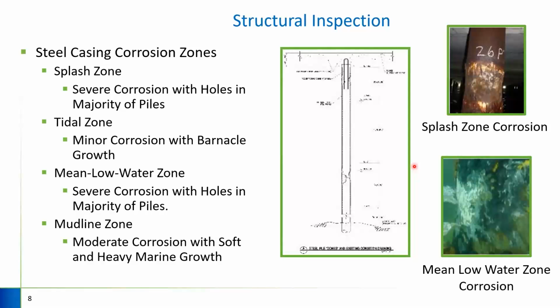And as you can see here in the upper right-hand corner, the corrosion was pretty severe and could potentially affect the structural capacity of the final elements. Additionally, in the mean low water zone, we saw similar severe corrosion, typically between about 0.2 and 0.3 inches, so about 40 to 60% of the steel thickness of the pile.